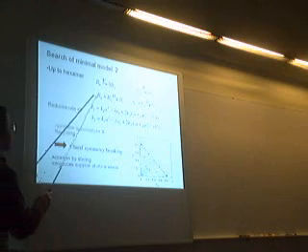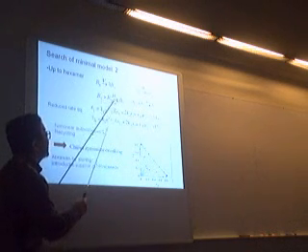So up to here, with only monomer incorporation, you cannot break the chiral symmetry. So I have to go to hexamer and break the hexamer into 3 dimers. But with only this process it is also not possible to break the symmetry. What I really need is this: 2 dimers forming a tetramer, and this breaks the chiral symmetry.